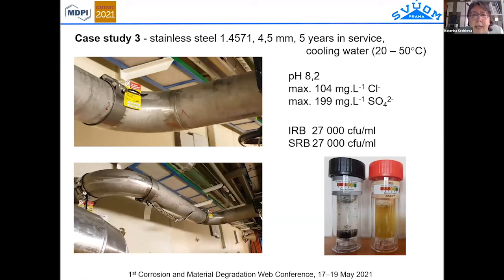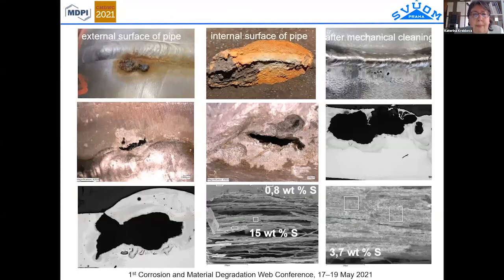Case study 3 is stainless steel. After 5 years in service, it was a cooling water system. In this system was a relatively high content of sulfates, and we identify a relatively high content of both the main types of bacteria which are connected with microbiologically induced corrosion. On the external surface of the pipe there were places where we identified penetration, leakage, but on the inner surface was a relatively homogeneous layer of biofilm, and after cleaning a lot of pits were identified.